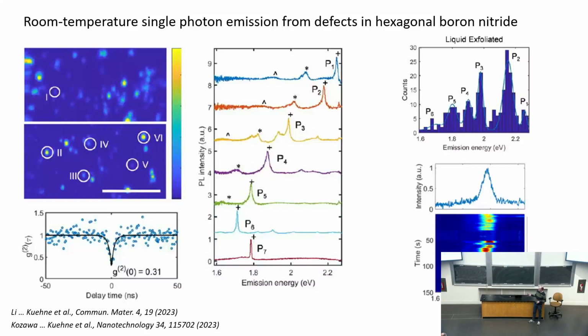But these defects that people find on the surface of hBN can be single photon emitters. So here the single photon emission is shown in this autocorrelation function of a specific spot that emerges when you do PL or you scan on the surface of hBN. And there's a couple of things that we notice. First of all, there's a whole bunch of different types of emitters. So they have all different energies. And so there's a whole discussion of what these emitters actually are.